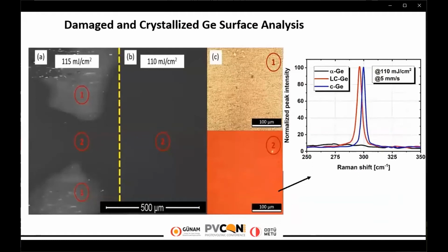To get much knowledge about the sample morphologies, laser crystallized regions were analyzed with scanning electron microscope, SEM. For the sample processed with a laser fluence of 115 millijoule per centimeter square, structural deformation is clearly visible as a large crater and heterogeneously defective region formation in picture A. On the other hand, consistent with optical image, the sample processed with 110 millijoule per centimeter square shows homogeneously smoother surface morphology after the crystallization process.